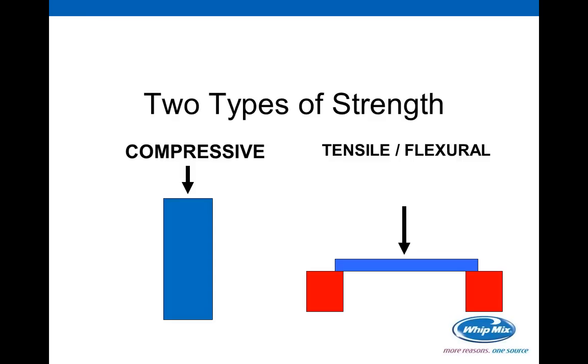You need to know that gypsum does not have good flexural strength. Much like glass, for example, you'll notice as you drive around, those companies that deal in glass always transport their glass standing on its edge. They don't put it down flat. Why is that? Well, standing on the edge generally gives it a little more compressive strength. If they do lay it down flat, it needs to be laid down on a surface that's absolutely flat with nothing underneath it. If you take a piece of glass and lay it on the floor, let's say a nice vacuumed carpet floor that's absolutely flat, you can walk all over it without any problem. Take a little BB and put it underneath that glass and then walk on it, it's going to break.